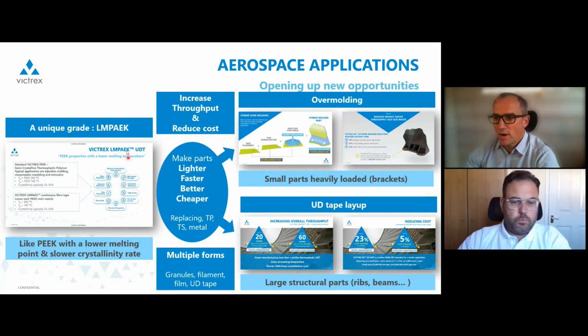We started with this pretty unique grade, LMPAEK obviously, which allows us to make parts lighter, faster, better, and cheaper, because overall the objective is to increase the throughput for aerospace and also reduce the cost. We can replace existing thermoplastic parts, thermoset, or even metal. We are targeting 2 main applications. One is overmolding, for small, heavily loaded parts, like loaded brackets. The other is UD tape layup by AFP, automatic fiber placement, where we can achieve pretty high speed and pretty good quality, targeting larger structural parts like ribs and beams. So that was really to give a high-level overview of what LMPAEK is, where we have a good fit, and where we are today.